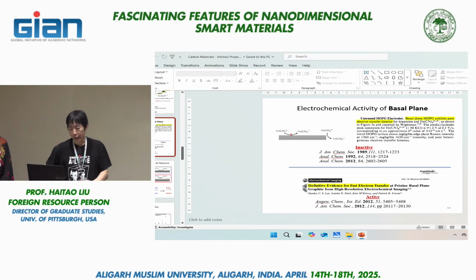So, as I said, there's this very different outcome in the electrochemical measurement. And from our view, whatever has been reported for the inactive behavior is due to surface contamination. Now, this transition would be, in my view, from active to inactive. So active is the intrinsic behavior. Inactive would be the extrinsic behavior.